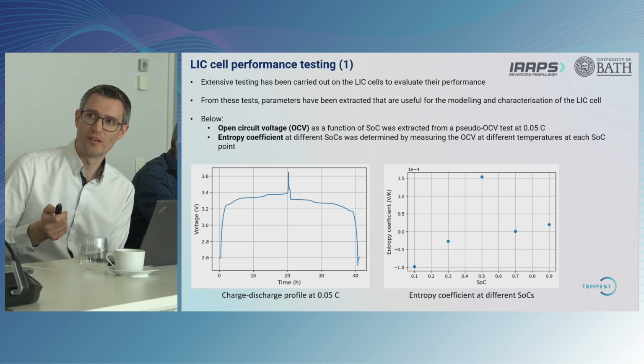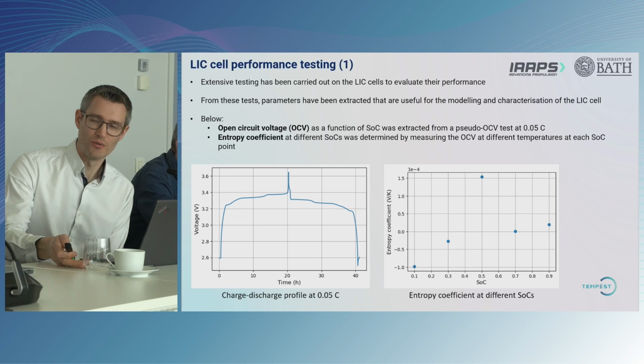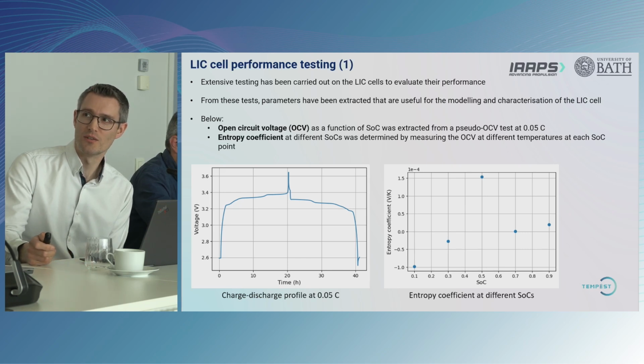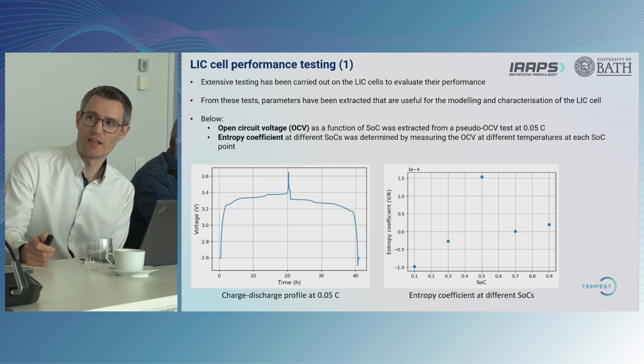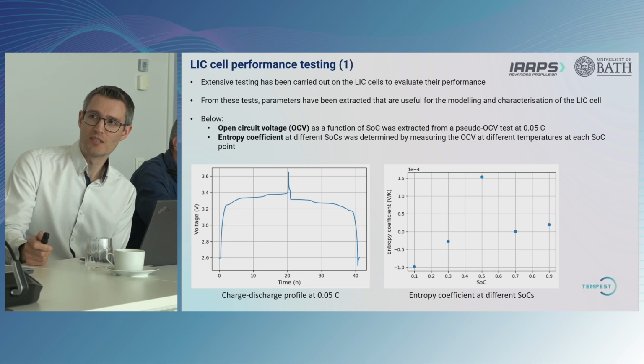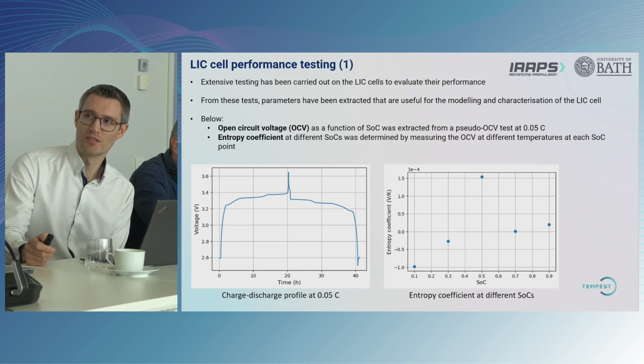We started with a conventional open circuit voltage test. So this is a pseudo open circuit voltage test at an extremely low C rate, so you can at 0.05 C. You can see the results of that in the bottom left-hand corner. And the perhaps more interesting element to this is we characterized the entropy coefficient, which is a nice piece of data, because this kind of data is not very widely available.